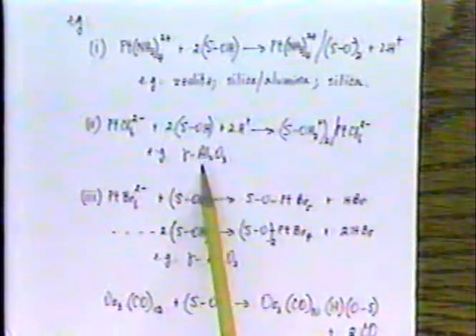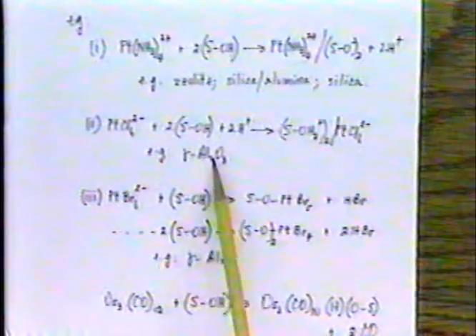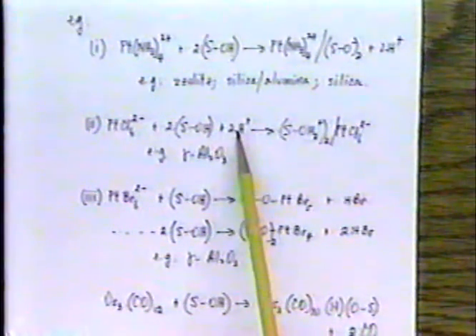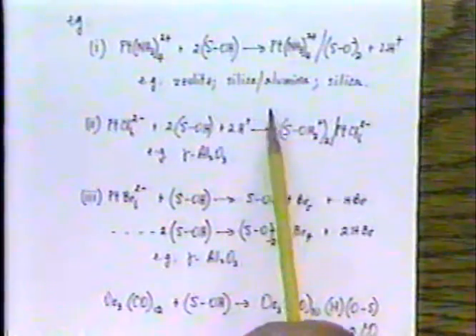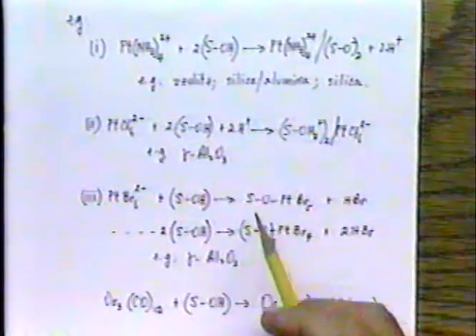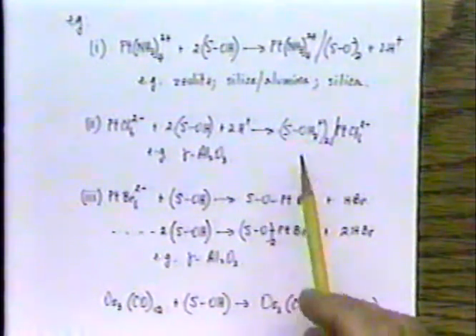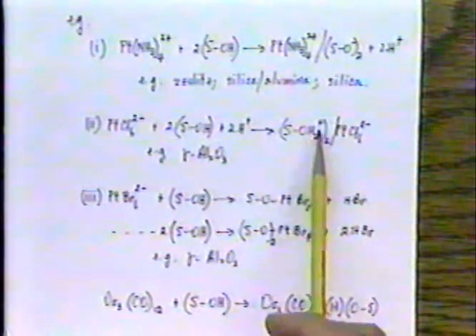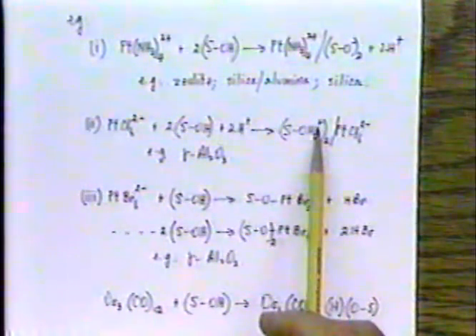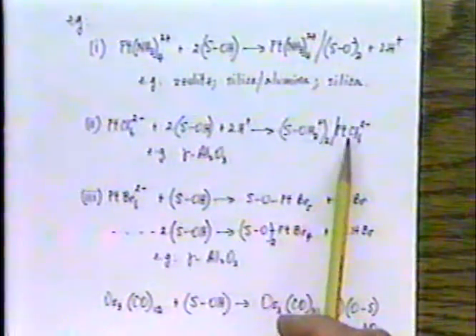As I've suggested, there are some groups on the surface of gamma alumina that are basic, but a better example perhaps would be the OH groups that are present on the surface of magnesium oxide, which are strongly basic and which can undergo a reaction of that sort. Binding a proton generates a site with a positive charge, which can then bind a negatively charged anion.